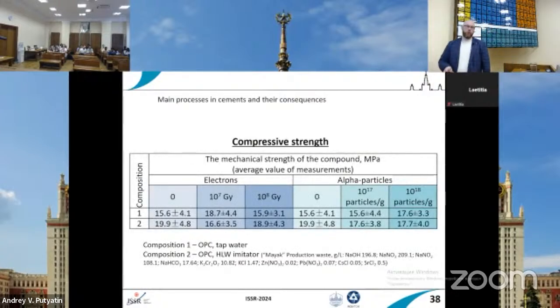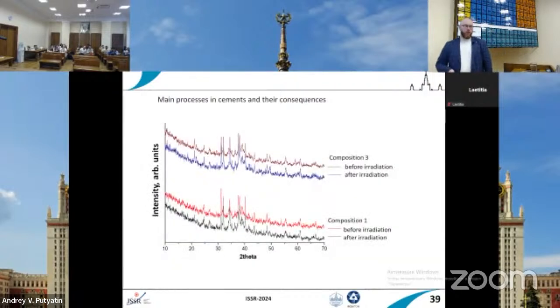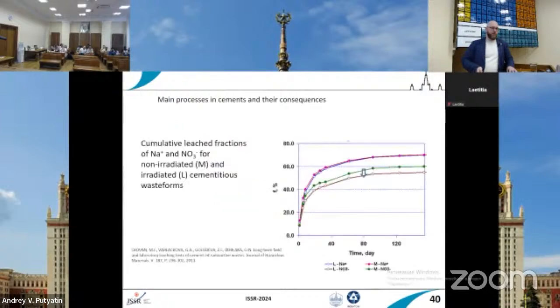We also performed some study with the ordinary Portland cement without and with high-level waste simulator. So it was not an active solution, it was just stable elements that were immobilized in this cement matrix, and we irradiated them with electrons and with alpha particles, and you can see that the compressive strength is almost the same within the uncertainties. Also, the mineral phase composition, so there is no indication of the mineral phases, just the comparison of the XRD patterns, but you can see that they're almost the same, just a few deviations.